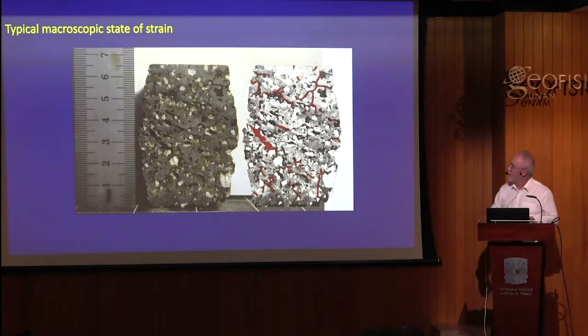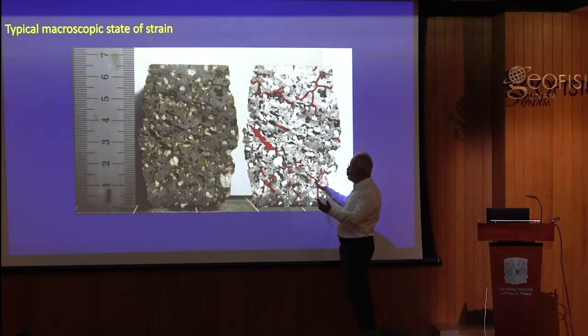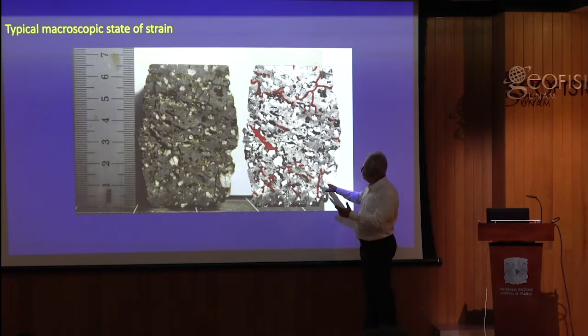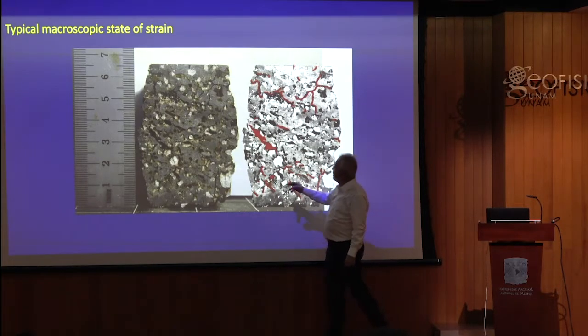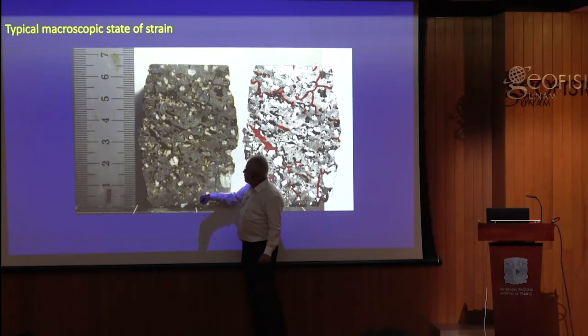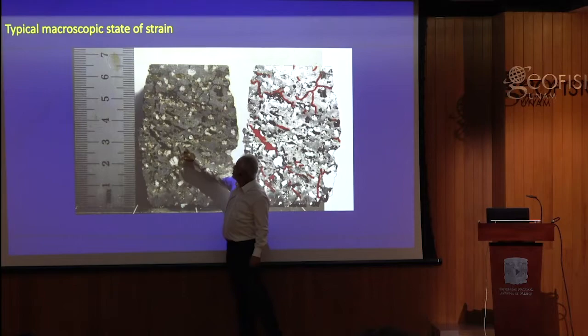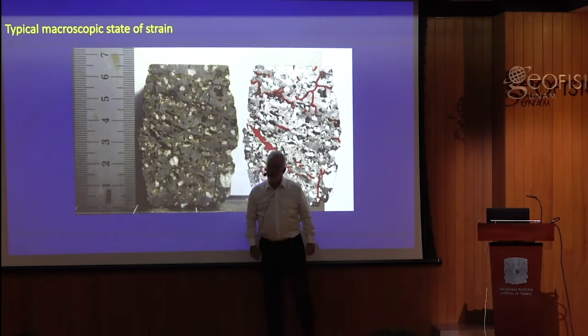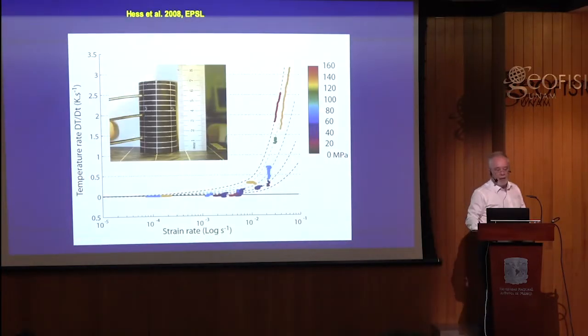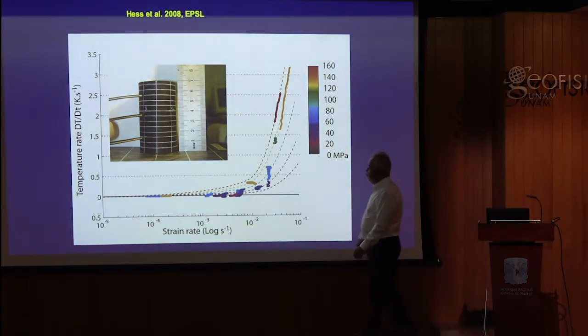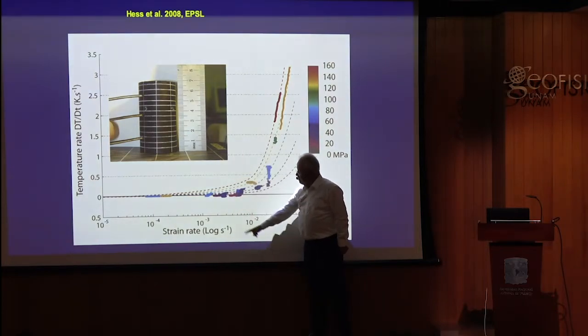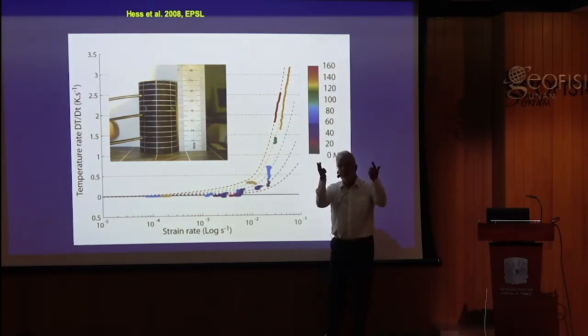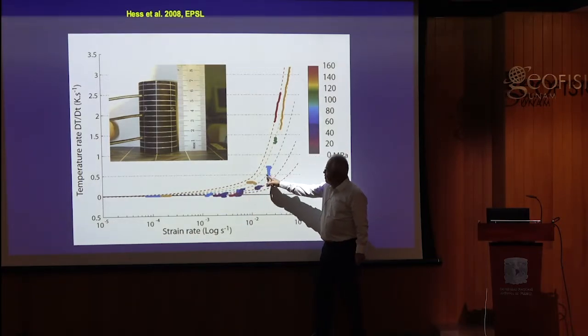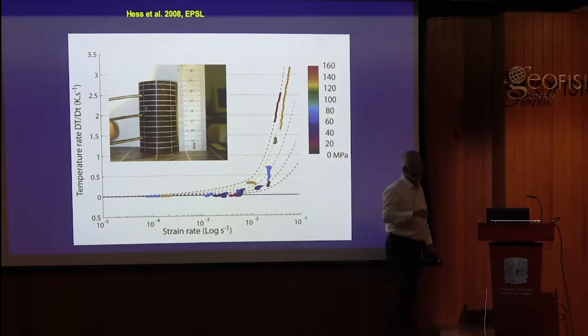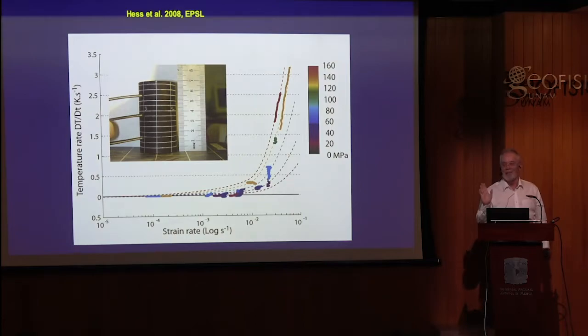This is what a rock looks like, a volcanic rock, when you do the same thing. These are both post-deformation, of course. These are different projections of the same. You can see a barreling of the sample. You can see we're talking about composite materials, multi-phase materials. Here are the crystals, and some of these black parts here are the actual bubbles in these dome rocks. And if we squeeze them, we can watch the temperature increase. This is temperature versus strain rate. The faster you go, the more the temperature rises because the heat cannot dissipate. These are good insulators. And you start to see the temperature climb, climb, climb. If we change the temperature, we change the viscosity of a system. It really gets complex now.